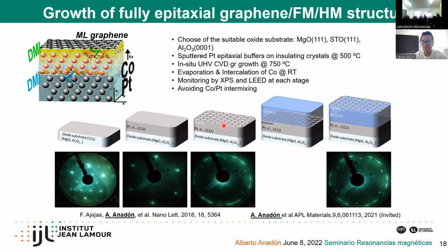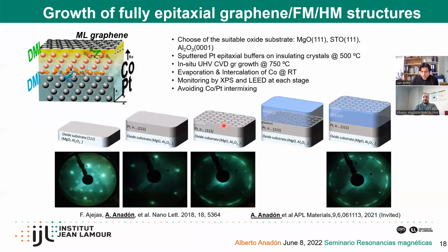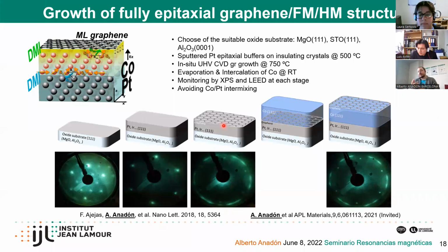Normally in a monocrystal, you are not able to do this because the monocrystal has almost zero resistance, so you cannot apply any current through the graphene itself. But in this case, even though you still have some metallic material, which is much more conducting than graphene, the proportion is much better for devices. I don't know if I answered your question.